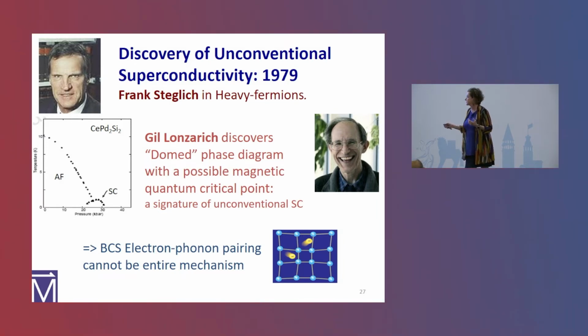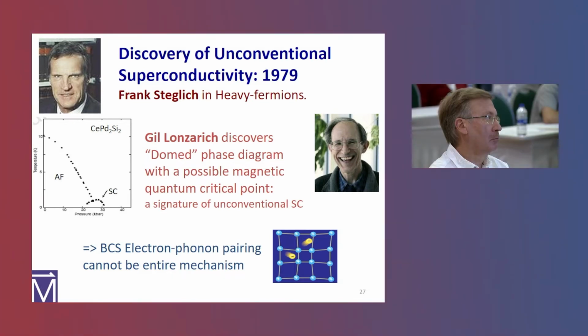But what's so surprising is that we have antiferromagnetism on one side and Fermi liquid, a normal metal, on the other side. And here's the crossover across this line. Then when you get down to lower temperature, these phases fight each other, which is determined to be a quantum critical point in most of these things, and this dome of superconductivity appears. Why does that happen? Very interesting. But the fact that it's near magnetism, as we all know, conventional superconductors really hate magnetism, right? So why is magnetism all of a sudden good for superconductivity? It became clear that BCS electron-phonon coupling couldn't be the only story here.